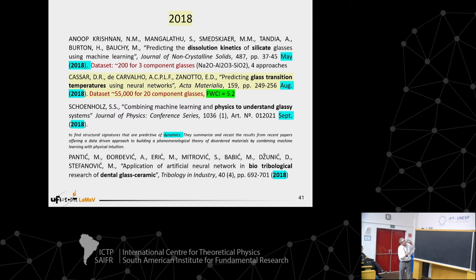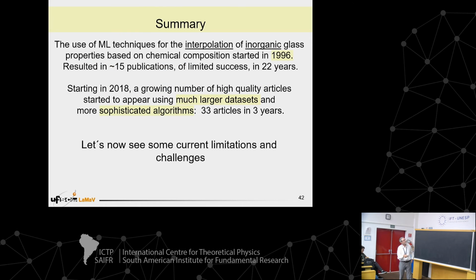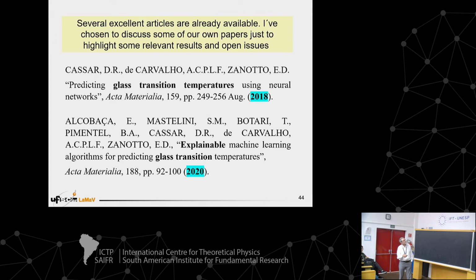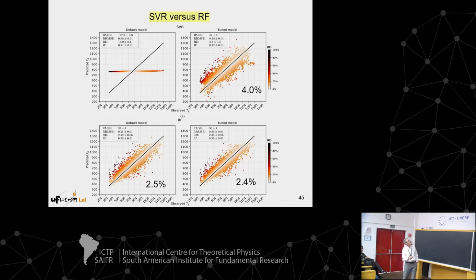Anyway, the key thing here is that we trained a particular artificial neural network algorithm with 55,000 data, composition and TG, in this particular case, the glass transition temperature. That particular temperature is very important. And then we published a few other papers, and this is the result, testing different algorithms. SVR is a type of algorithm. Random forest is another algorithm. And this is, for instance, the predicted value by the algorithm versus the measured value of the glass transition temperature.